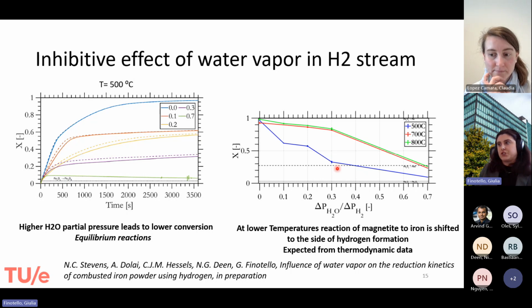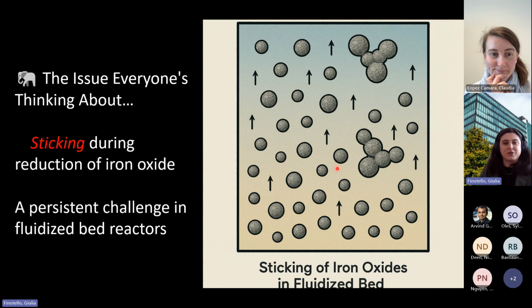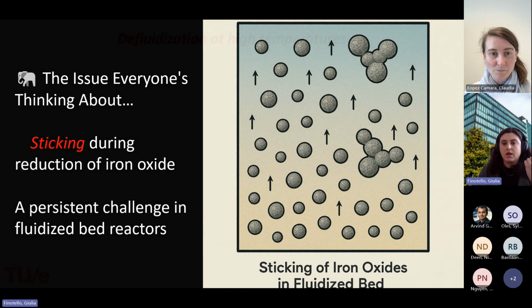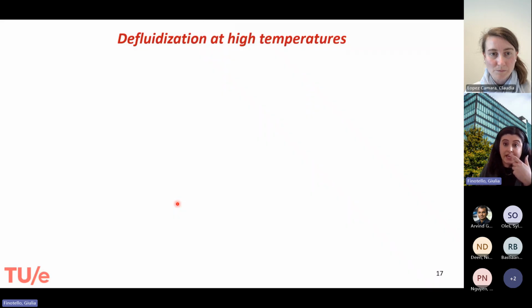Okay, this is all interesting, but there is an elephant in the room, which is the issue with the sticking during the reduction of iron oxide, both in the fluidized bed as well as the shaft furnace. So that's a persistent challenge in the fluidized bed reactor, which is indeed the sticking, the clustering of the particles that are sticking together. And what in practice do we see? Why do we not want this sticking? Well, because we can have defluidization at high temperature.